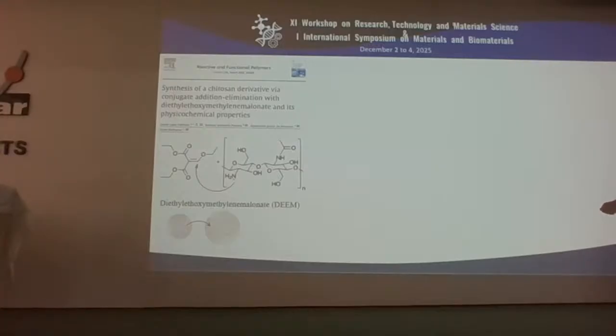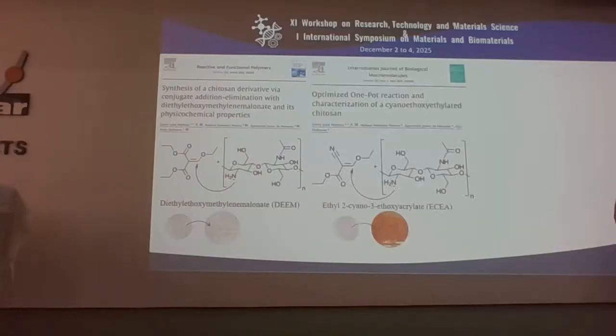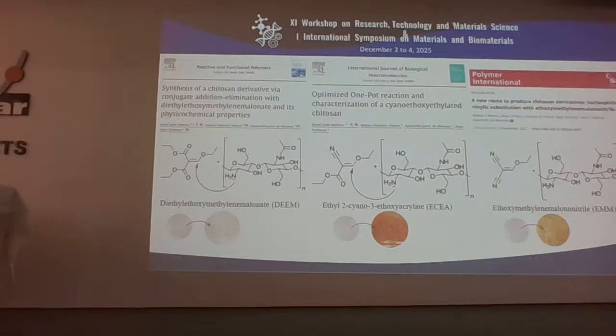The first one is a dual ester, and you can see almost no change in the color after the modification. The second one is with 1 cyano group. Now you can see a yellowish, brownish color of differentiation. And the third one is with 2 cyano groups. I'm trying to understand what kind of group in the chitosan can change the absorption of the crystal violet. And you can see a yellowish color.